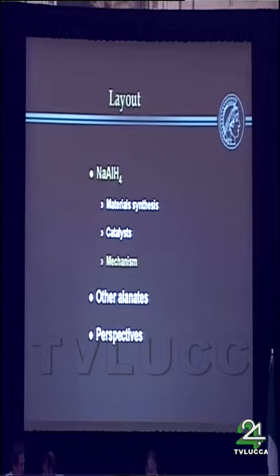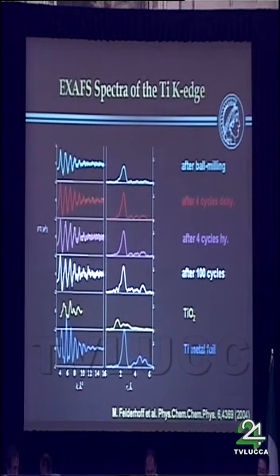Mechanism: Andreas Züttel has already said that's one of the crucial or most difficult questions we are still facing. I think there is at least agreement on the state of titanium since roughly a year. We published an EXAFS and XANES study, which was subsequently corroborated by almost similar data from the Brookhaven team and Maximilian Fichtner's group. The EXAFS spectra basically tell you that the local environment of the titanium does almost not change during cycling. After synthesis, rehydrogenated, dehydrogenated, the state of the titanium remains pretty much the same.